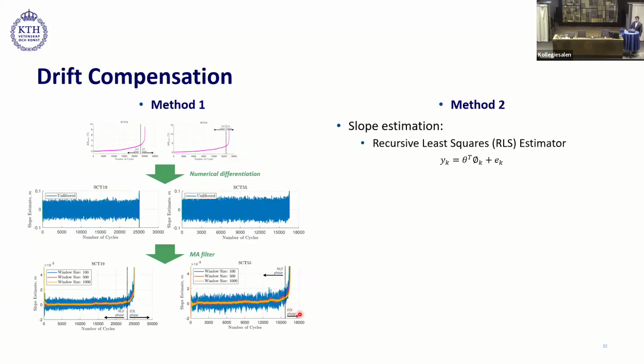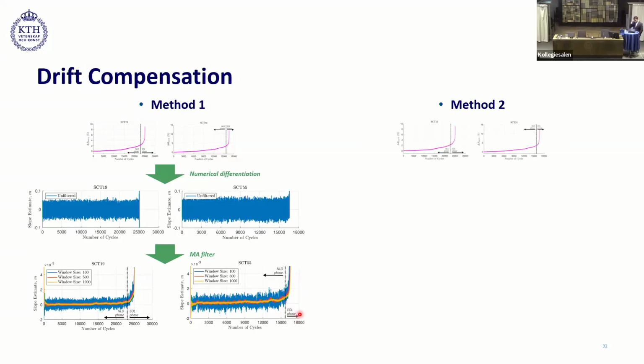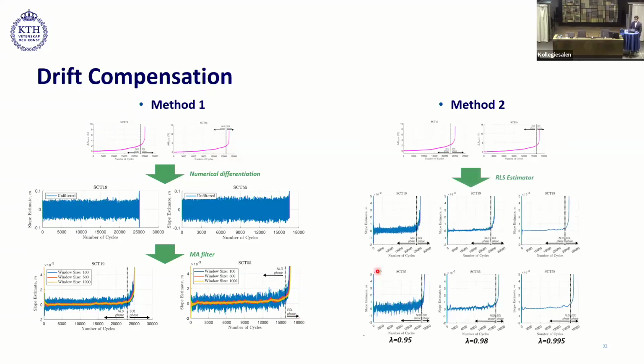We also developed a second method which used recursive least squares estimator. So here we fed the temperature compensated signal into the RLS estimator, and it directly gives the slope estimates. One important thing to note in the recursive least square estimator is the term lambda, which is called forgetting factor. So the value of lambda is selected depending on how fast your signal is changing. If the signal is changing fast, then it should be lower. But in our case, we have a slow increase in the beginning and then a very fast increase in the end.